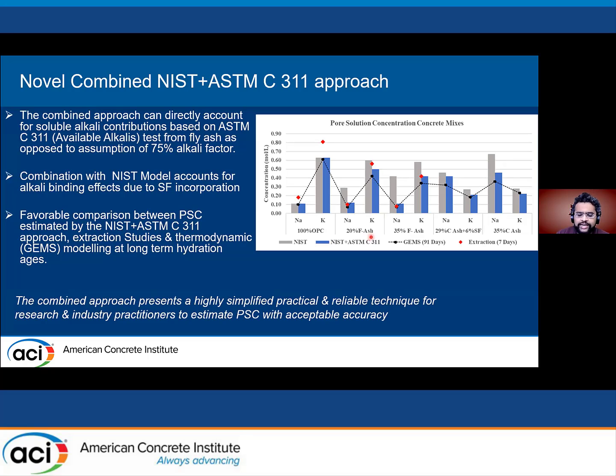But we really see beautiful results when we look at class F fly ash incorporation, because earlier we saw that class F fly ash contribution to available alkali is significantly lower than the cement. Although the bulk alkali may be higher, the available alkali is lower. So assuming a default percentage of 75 may not be an appropriate method, and we see a huge difference in prediction between the two approaches. Now, when you validate this with the extraction studies, the values for the combined NIST and ASTM C311 approach match pretty well with the GEMS modeling, the thermodynamic model, and also the extraction studies.